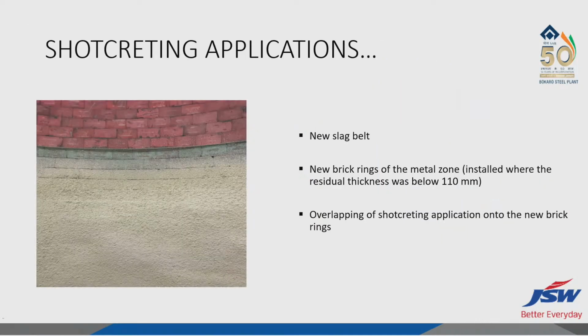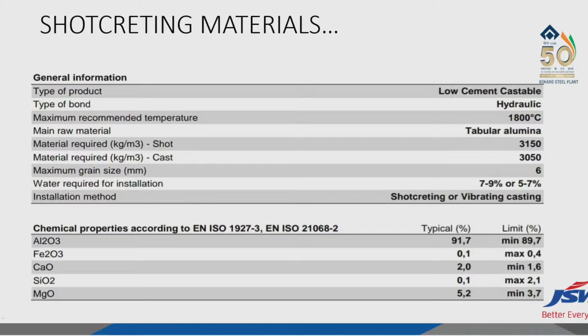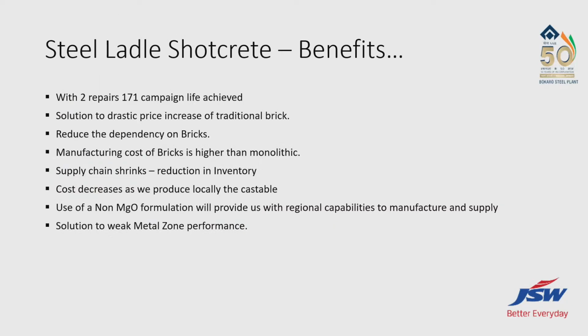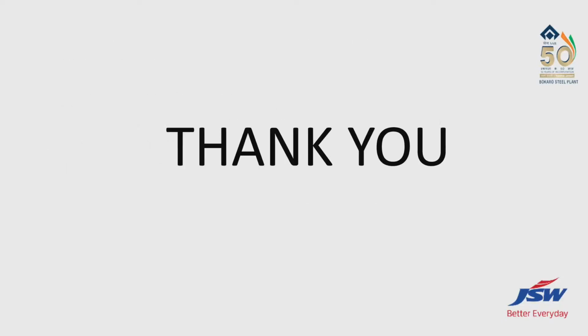This is the after application photos. This is the typical material being used, tabular alumina based raw material, and the alumina is 90%. And this is the benefit of shot treating. With 2 repairs, we have achieved a life of 171 campaigns. Due to monolithic use, we have drastically reduced the cost, and also it's locally easily available, so inventory cost can be reduced, and the non-magnesia based problem can also be resolved. Thank you.